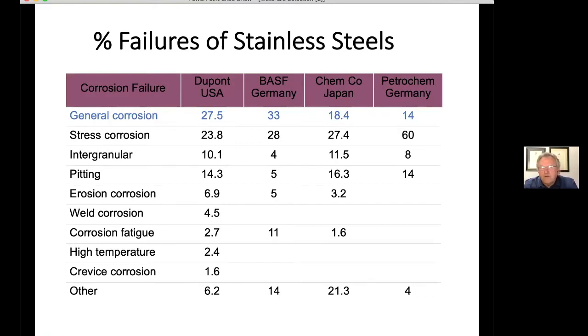This is not intended to show that stainless steel fails, but when stainless steel does suffer from corrosion failure, it is interesting to note that the predominant cause of that corrosion is not general corrosion. It is what we call localized corrosion. And you can see that there are a number of different types of corrosion that occurs: stress corrosion cracking, intergranular corrosion, pitting, erosion corrosion, crevice corrosion down the bottom. These are the predominant failure mechanisms for stainless steel, rather than general corrosion, which is the phenomenon that we see